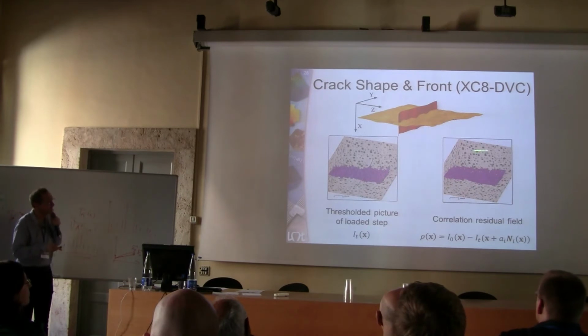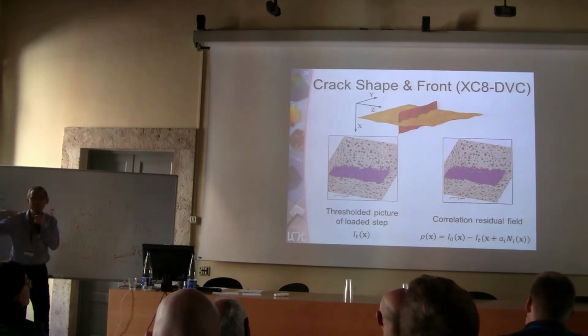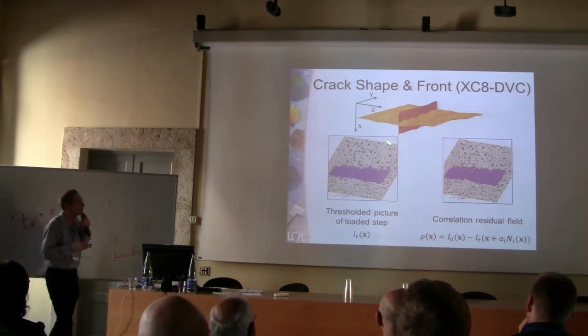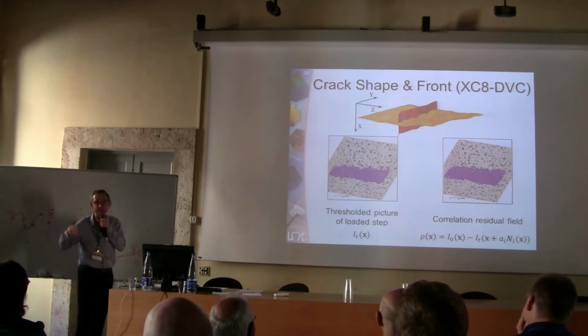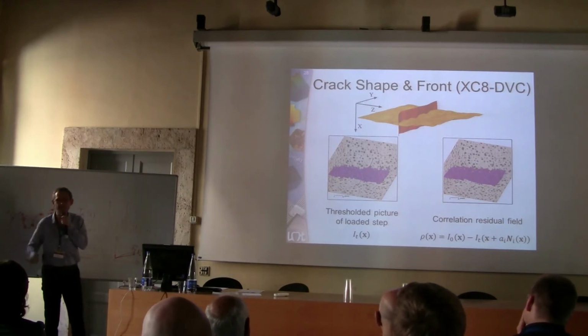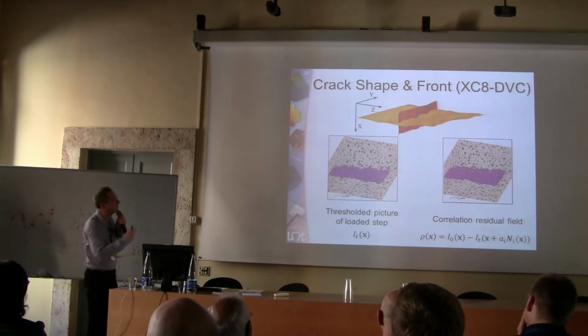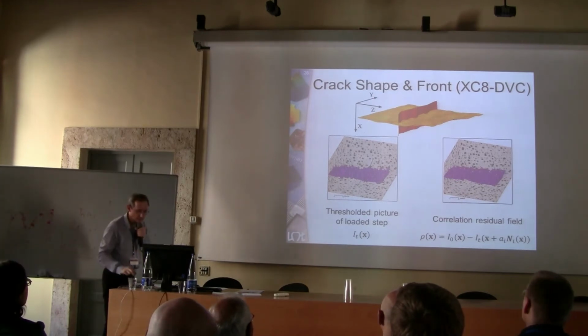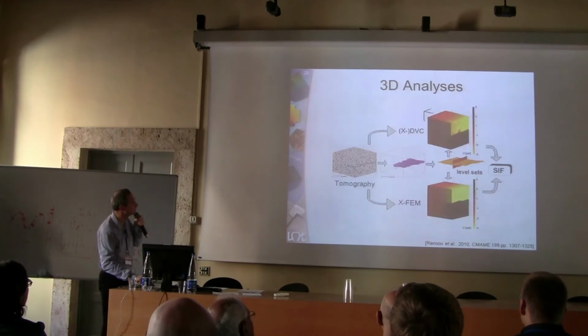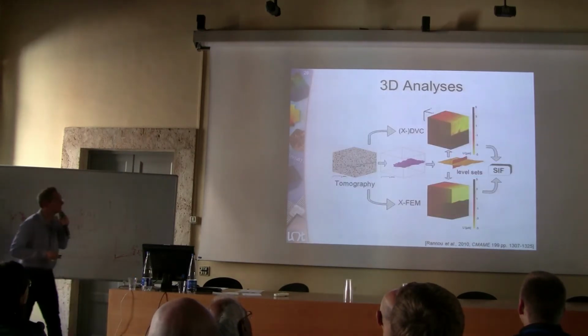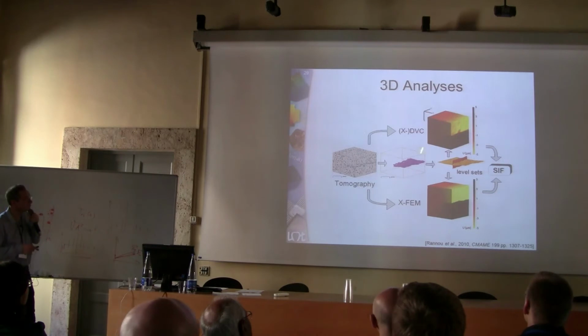And so then you can account for it, rerun an analysis, but this time with a kinematic basis that is exactly the one that you would use in numerical simulations, and you would enrich it with additional discontinuous contributions. This means that now you are able to analyze pictures for which you can reveal your cracked surface.